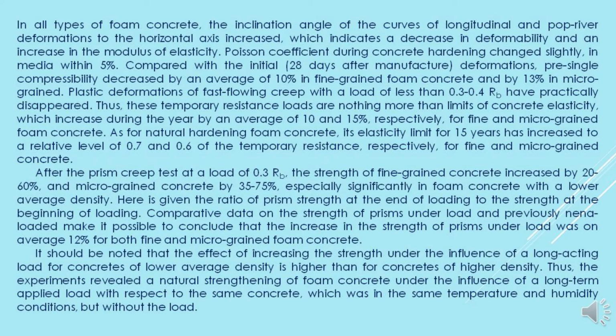Plastic deformations of fast-flowing creep with a load of less than 0.3–0.4 RD have practically disappeared. Thus, these temporary resistance loads are nothing more than limits of concrete elasticity, which increase during the year by an average of 10 and 15%, respectively, for fine and micro-grained foam concrete. As for natural hardening foam concrete, its elasticity limit for 15 years has increased to a relative level of 0.7 and 0.6 of the temporary resistance, respectively, for fine and micro-grained concrete.